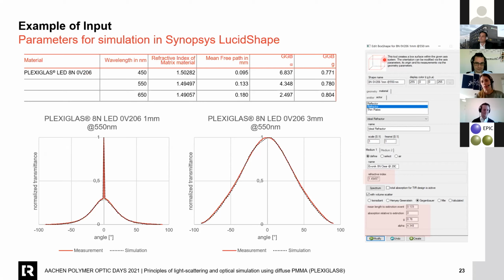And you can see that you enter the Gegenbauer parameters and you get the results in the diagrams. So plexiglass 8N LED 0V206 at 1 millimeter shows the unscattered light at 0 degrees. So you have a hotspot if you use this product with your light source. That's nothing you want to have.